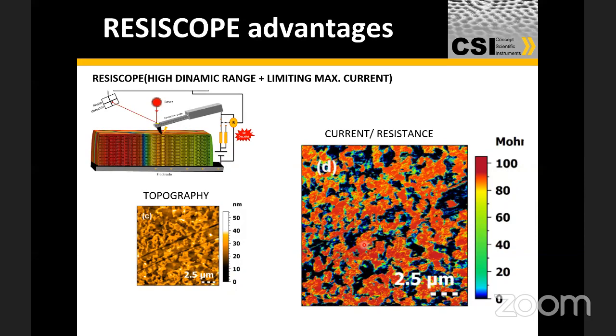Right. Maybe it's a good point to talk about this. Typically the sharpest tips you can get these days will be down to a couple of 3-4 nanometers. So obviously the resolution of the current or resistance map will depend upon how sharp your tip is, and normally tips meant for these kinds of measurements are the sharpest around. We only sell tips that we know are less than 5 nanometers in tip sharpness.